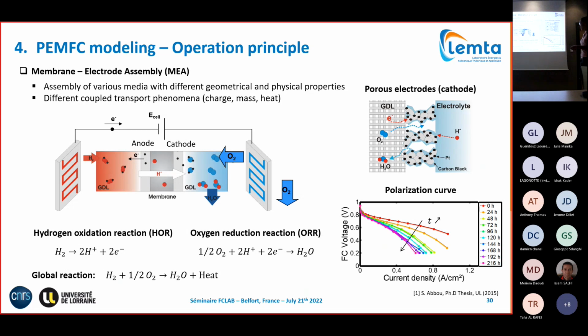This means the overall global oxidation reaction of hydrogen is separated into two half reactions. The membrane electrode assembly is actually composed of different materials. Just to say that an electrode is a porous material composed of different components: an electron conducting phase, mostly carbon; a catalyst, mostly platinum-based; and an ion conducting phase, mostly the same ionomer as the electrolyte membrane. And we need some pores in order to allow gases to access the active sites.